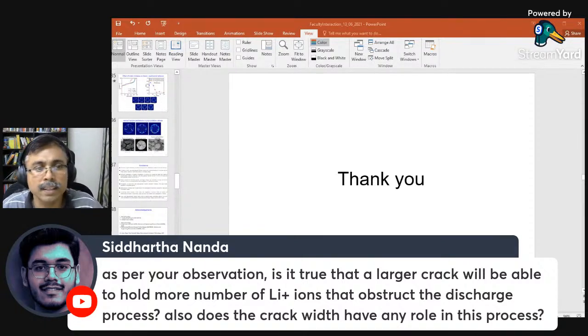Although the crack is shown experimentally to be very fine, with no real crack width, this diffuse interface model shows a crack width, so it is all about how the transport is degraded. Once the crack is developed, across the crack no transport will happen, but the crack is developed in this direction, so radially it can still maintain some of the transport. But the mechanical stress field is also very interesting in how it will hold.